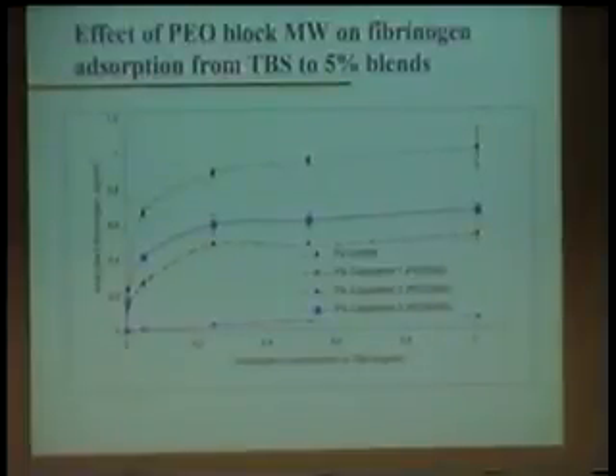This shows the effect of the PEO block molecular weight on adsorption, and they're all loaded at the 5% by weight level. So I've got four surfaces here: the control, which you saw in the last slide, it's the same, and then three blend surfaces containing copolymer 550, 2000, and 5000. And you can see that it's the lowest molecular weight down here which gives us the best result. As we go up in molecular weight to 2000 and 5000, they become less effective in terms of protein resistance.